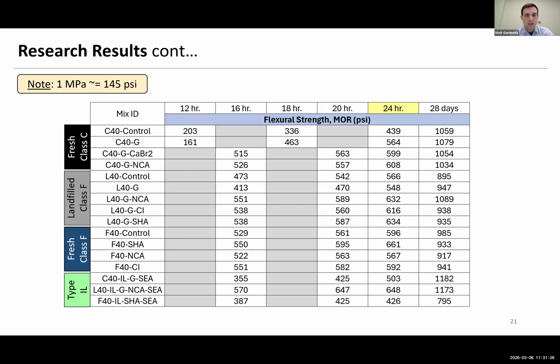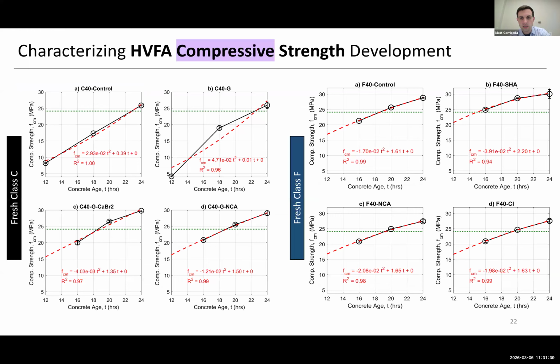We then also went to do flexural strength testing to help inform calculating the cracking moment, to make sure we don't crack the member when it's lifted out of the casting bed. And you can see here the results for those tests. The more interesting way to look at it, I'll come back to in a second.